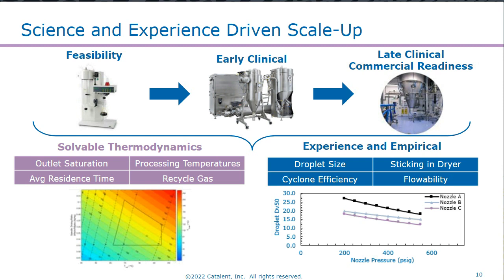Other things you need to consider during scale up and troubleshooting are more experience and empirical based. These are things like what size is the droplet atomized to? How efficient is your cyclone? Are you collecting 50% of your powder or 95% of your powder? And then things like sticking in the dryer. Do you have a lot of buildup on the chamber walls? And do you have good flowability of your powder for downstream processing?